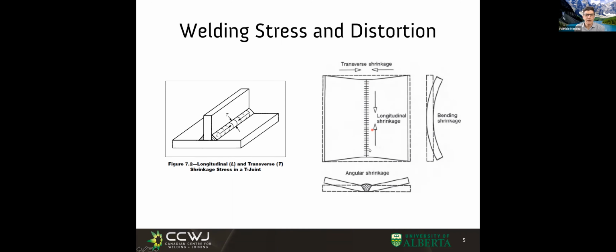Along the axis of the weld, we have a longitudinal shrinkage. Across the axis of the weld, we have a transverse shrinkage. In addition, if I weld the plate, they tend to be distorted. If I weld two flat plates, typically they don't end up flat. And I showed you some images when we discussed the concept of joining, about how things like electron beam welding could give low distortion in thick sections, but TIG could end up with big distortions, angular distortions in thick sections. And then here we have bending shrinkage.